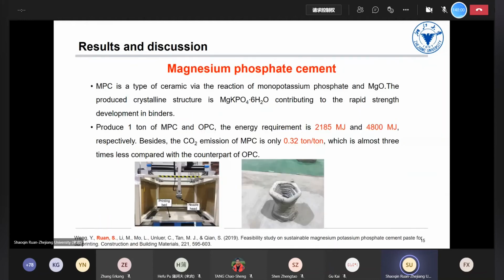That is magnesium phosphate cement. We conducted several studies about its feasibility in 3D printing and found it's quite effective because it is rapid setting. MPC is also a type of ceramic formed via the reaction of monopotassium phosphate and MgO. The produced crystal structure is struvite, contributing to rapid strength development in binders. To produce 1 ton of MPC versus OPC, the energy requirement of MPC is much lower, and the carbon dioxide emission of MPC is only about 0.32 ton per ton of MPC, which is almost 3 times less than that of OPC.